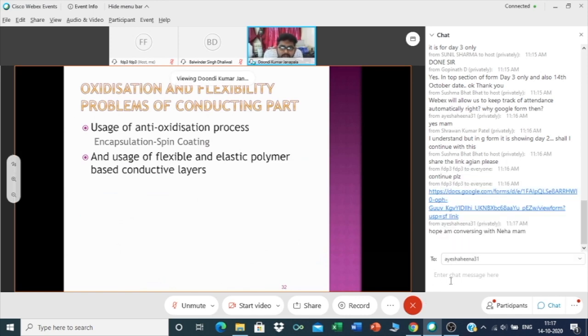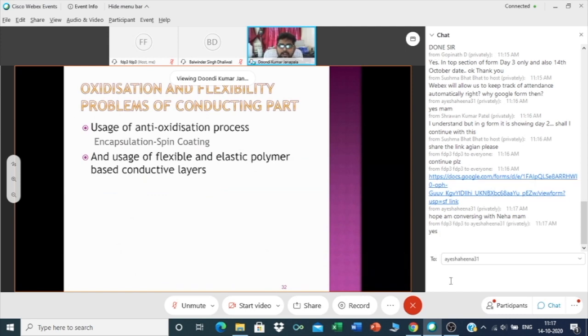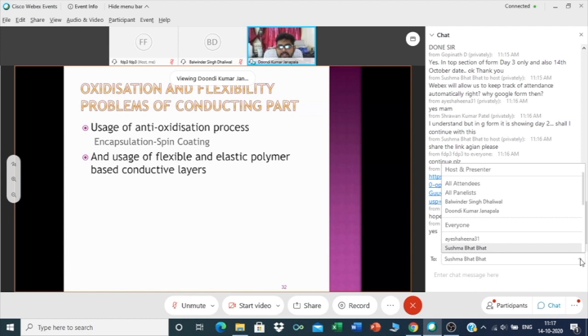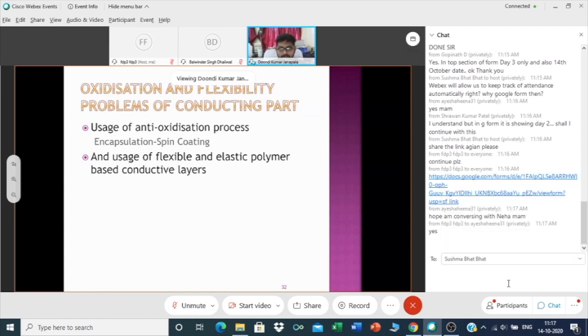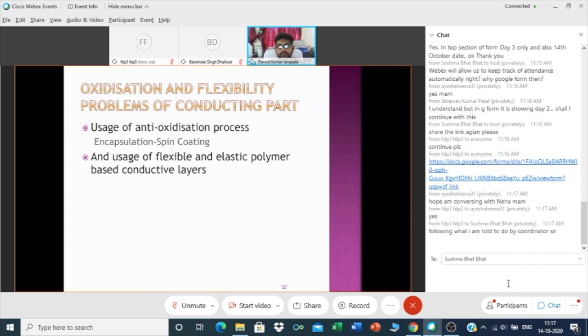So when you are working with conductive particles, there are 3-4 problems that you will face. The first thing is, some people after coating the nanoparticles will try to bake it. No, don't do that. That high temperature will spoil your nanoparticles, and they will get oxidized and break. Another thing is, after some usage, in any antenna that we work with, even your normal copper resist material, when you put it outside, after some time it will lose its color, it will get oxidized, and its performance will degrade. Similarly, the nanoparticles that we coated will get oxidized eventually over time, and the performance will slowly degrade over the time of usage.